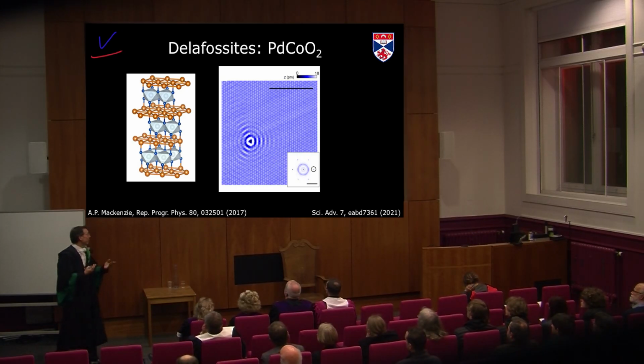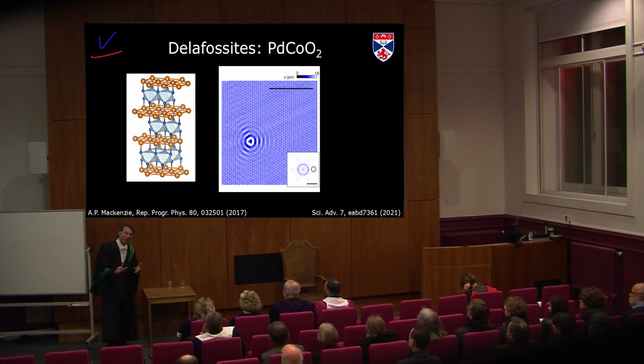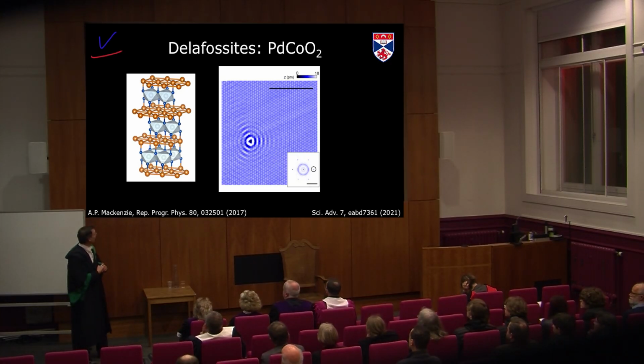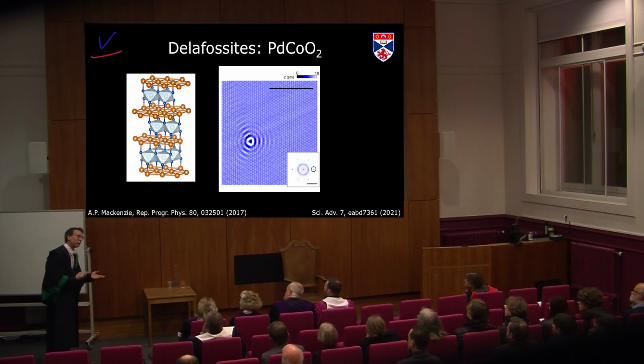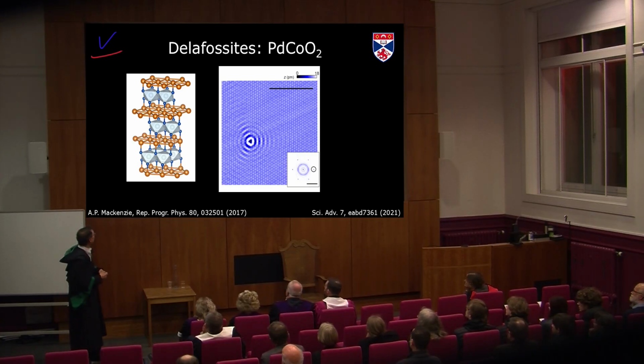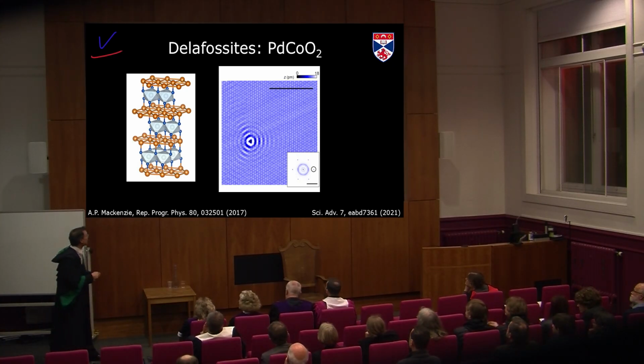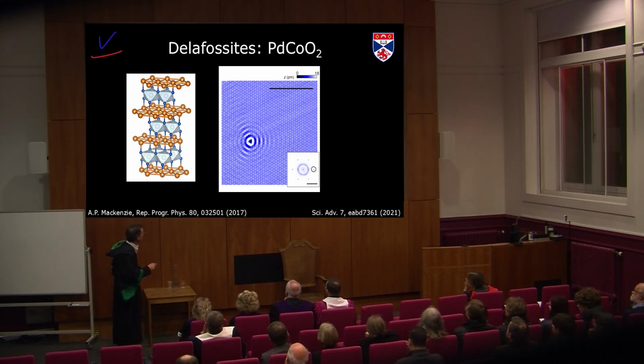And what's peculiar about this material is that electrons can move very easily in the material, which is surprising given that it's an oxide. Normally you would say in a metal they can move easily, but in an oxide you would say they cannot move so easily. And so we were trying to look at whether we can see in our microscope why they move so easily or how they move in the material. So we break these crystals, and then you would think, well, either you end up with these palladium atoms at the surface or with these cobalt oxide atoms, so it requires a bit of work to figure out what one sees. But this is the cobalt oxide surface of the material.